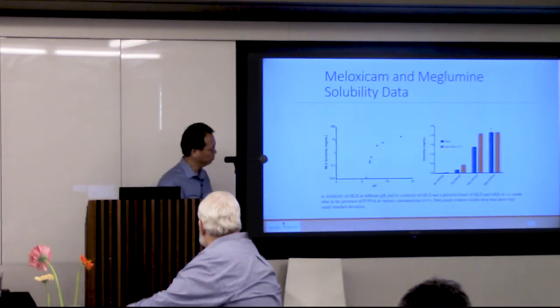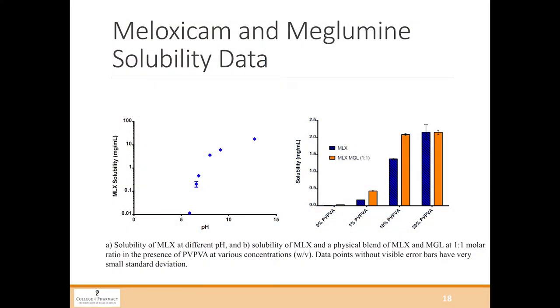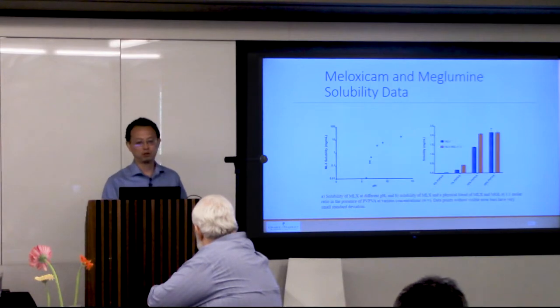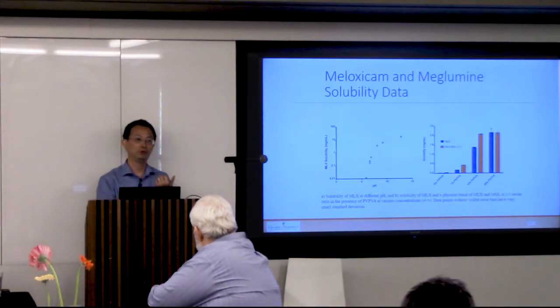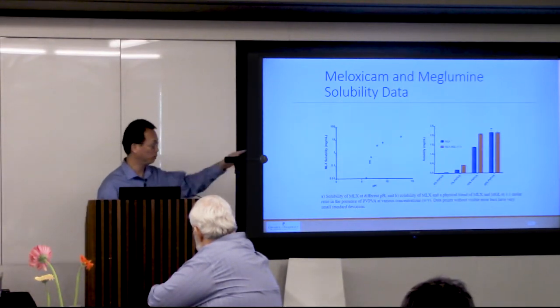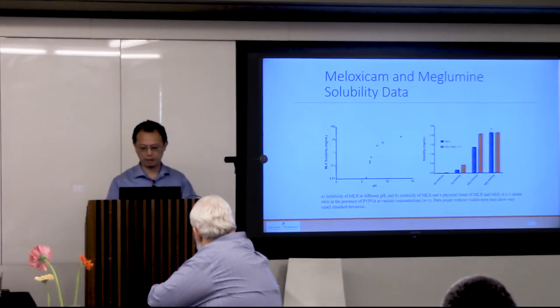So going back to the meloxicam solubility profile, solubility is very low. Once you hit pH 6, it starts to go higher. One thing we found interesting: in the presence of meglumine, solubility is high just because of the microenvironment pH effect. Meglumine itself will serve as a buffering agent and increase the solubility. We also find something very interesting when we have copolymer present. The copolymer itself will interact with meglumine and increase solubility. We're really trying to understand what's happening there.